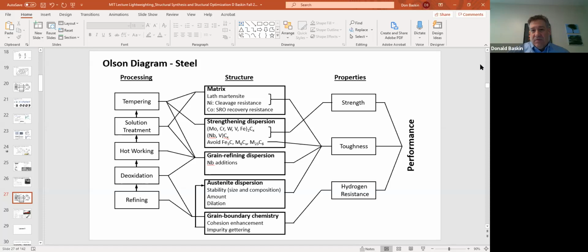Adding nickel in the refining stage will increase the cleavage resistance of the material, so the sort of grain-to-grain strength. The strengthening dispersion, so that's the precipitation hardening, that requires tempering. So you can see there's a link between tempering and the strengthening dispersion. Grain refining. Remember I talked about Columbus tubes on bicycles and niobium. So niobium is often added as an alloying element to steel to decrease the grain size and increase the strength.